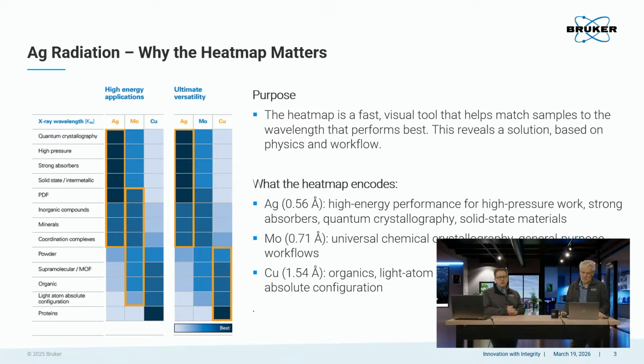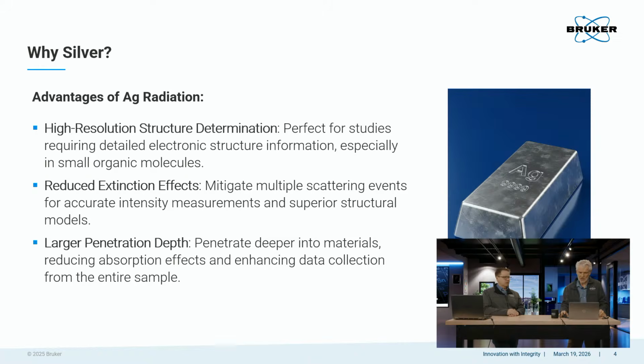All right. And with silver too, we need to remember it's not just about getting a silver source, because you can get silver sources in different places. It's really this silver source that is the one, because of the heat dissipation and the better technology, but also because of having that detector. The color coding of that heat map really includes the intensity of the source and the sensitivity of the detector. If you produce a lot of diffraction from a silver source, but you cannot detect it, silver doesn't help you. So things have to come together.